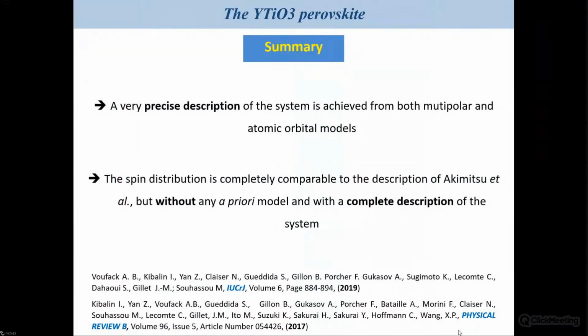So the difference here is, in our case, we don't make any a priori assumption on the spin distribution in the model. We just completely describe the charge and spin density of the system, obtaining a very precise description of the system using multipolar or atomic orbital models. And this is, at the end, completely in line with the work done by a Japanese colleague before, but without any a priori, and with a complete description of the system.